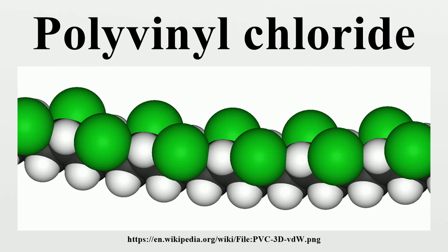Microstructure: the polymers are linear and are strong. The monomers are mainly arranged head to tail, meaning that there are chlorides on alternating carbon centers. PVC has mainly an atactic stereochemistry, which means that the relative stereochemistry of the chloride centers is random. Some degree of syndiotacticity of the chain gives a few percent crystallinity that is influential on the properties of the material. About 57% of the mass of PVC is chlorine. The presence of chloride groups gives the polymer very different properties from the structurally related material polyethylene.